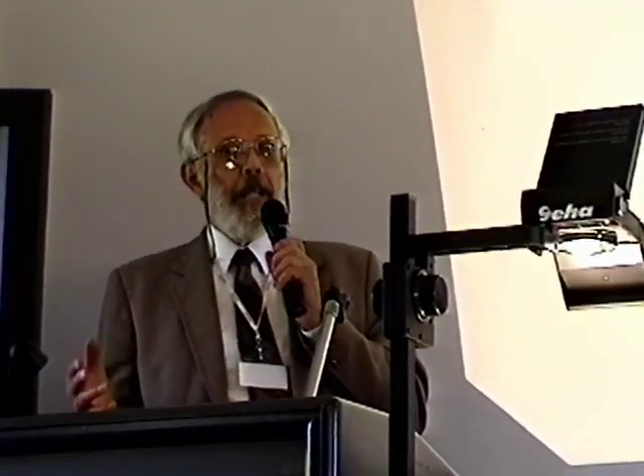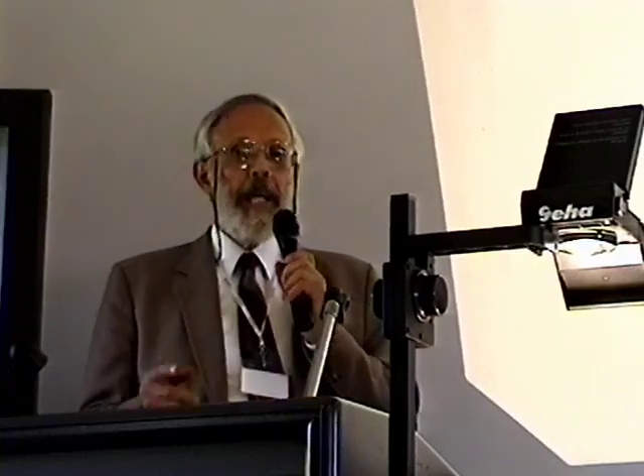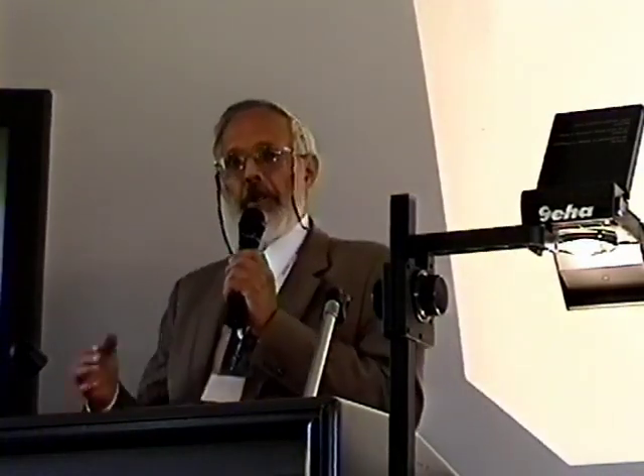Well, I might add one thing. The sample I'm describing here, I really don't have any good feeling for its history because it was used a number of times. It was sort of dark, and it looked a mess. The second sample that I made that worked was a clean piece of platinum that I electrolyzed for some period of time in lithium sulfate. When that was taken out of the lithium sulfate solution, and that's what Longchamp used, and put into the lithium deuteroxide, it was active immediately, but not to the same level. This went to 800 milliwatts, that one went only to 400 milliwatts, but it showed the same characteristics: the same tendency to want to die, and the same tendency to be resurrected. Obviously it was playing the same game. Lithium sulfate apparently is able to put down something on the surface that is more effective than I could get by accident.